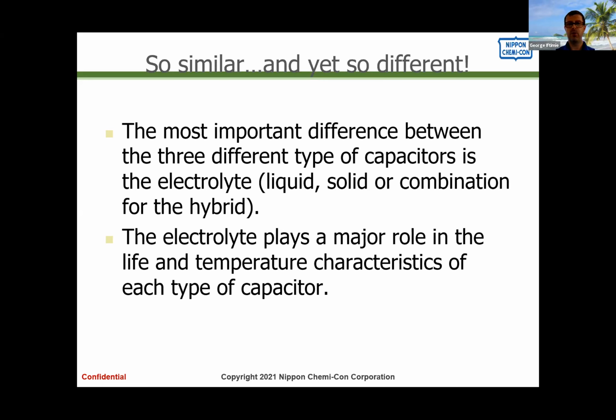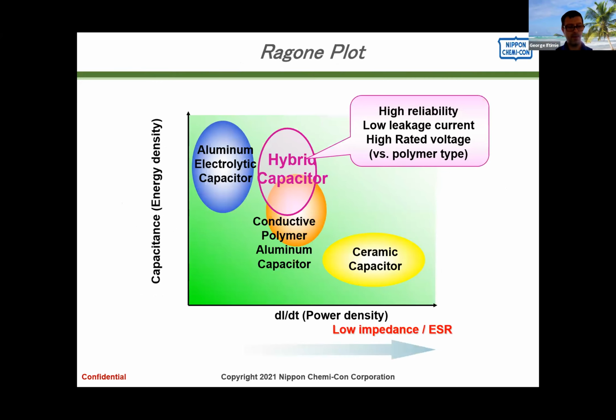But a thinner electrolyte is also more reactive, and it also tends to evaporate sooner. So there's always a trade-off between ESR and life. If you want a low ESR capacitor, you typically have to sacrifice life or endurance because that electrolyte will simply evaporate faster. And most people think electrolyte is lost through diffusion in an electrolytic capacitor especially, but that's not necessarily true. Most electrolyte is actually consumed by the capacitor to heal damage to the oxide layer. Some of the components, especially hydrogen, will eventually escape through the rubber bung, but the active portion of the electrolyte is basically used to create additional aluminum oxide.